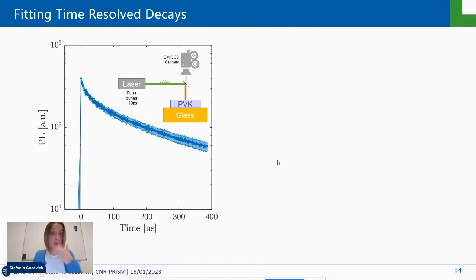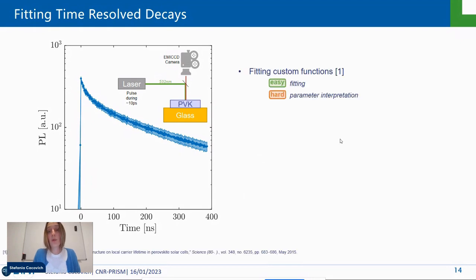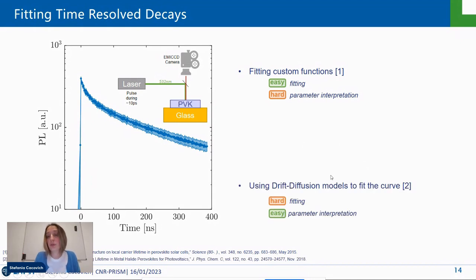But also on time-resolved decays, we can try to fit different parameters. However, this is quite a complex question to answer. Why? Because often in the literature, to fit this kind of decay, custom fitting functions are used, such as a bi-exponential or tri-exponential model. In this case, the fitting is quite easy, but on the other side, the parameter interpretation can be quite difficult because these fitting parameters do not have a strict physical meaning. It's also possible to use drift-diffusion models.